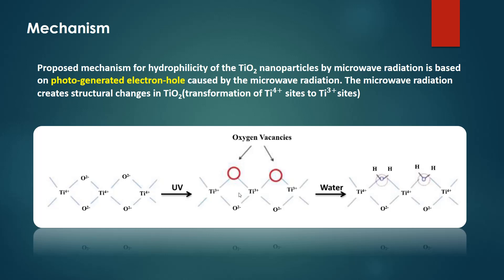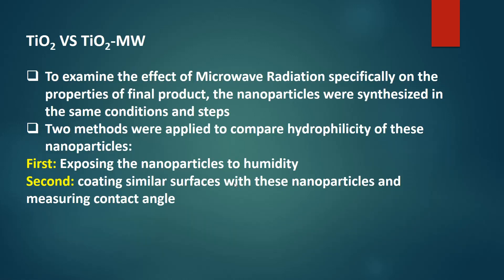Mechanism. The proposed mechanism for hydrophilicity of TiO2 nanoparticles by microwave radiation is based on photo-generated electron-hole pairs caused by the microwave radiation. The microwave radiation creates structural changes in TiO2 by transformation of Ti⁴⁺ sites to Ti³⁺ sites. This picture shows how microwave radiation can produce oxygen vacancies on the surface of nanoparticles.